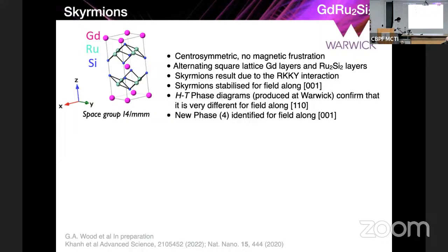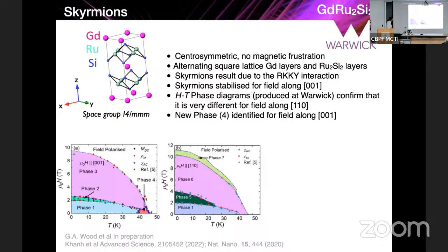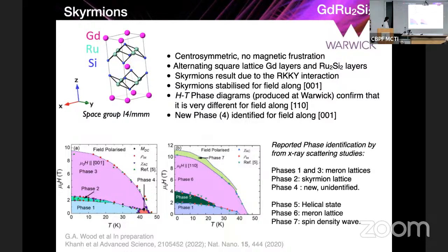You can actually study the phase diagram for H parallel to the 001 and H parallel to the 110, and the phase diagrams are very different. And this is the phase diagram that we've established at Warwick. And you see there are a lot of phases here that you can distinguish from AC susceptibility data. And by resonant X-ray scattering measurements, some authors have proposed what these different phases might be. And we have identified a further phase here, which is phase 4, the nature of this phase is still to be determined, okay?